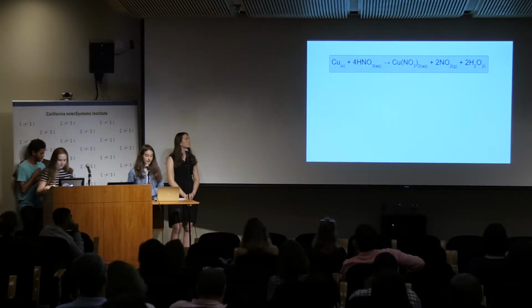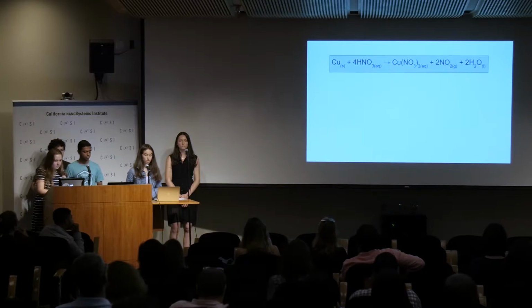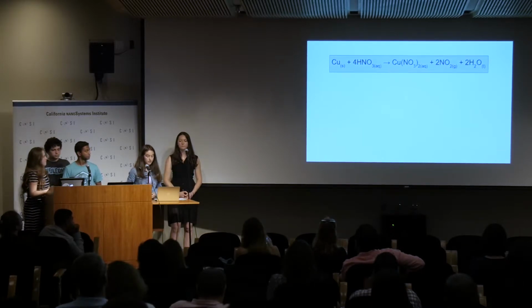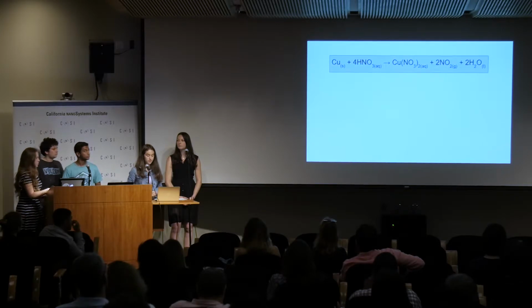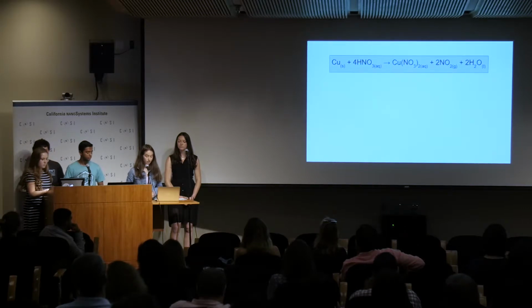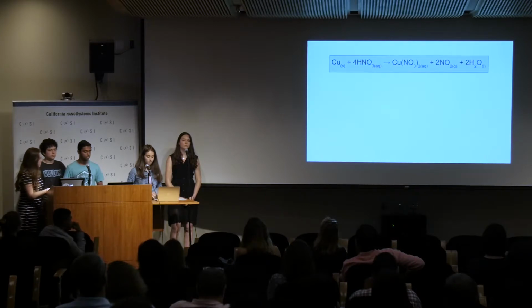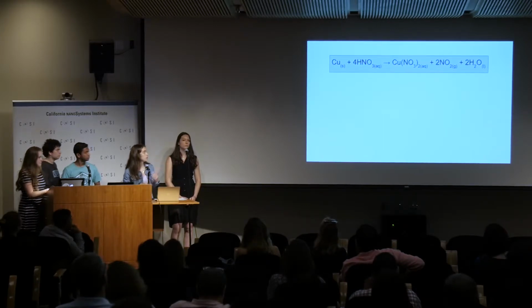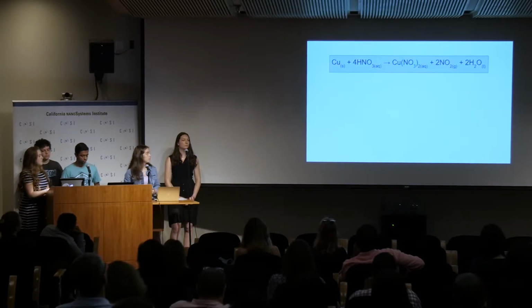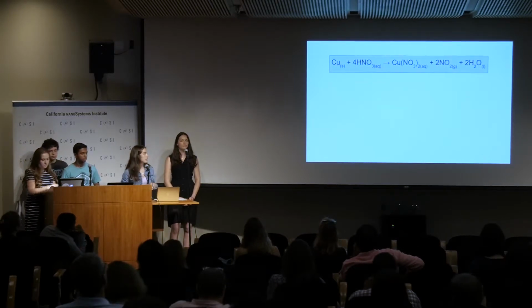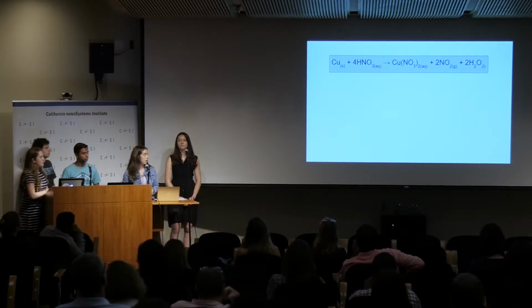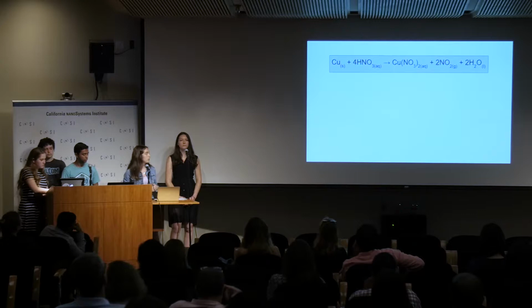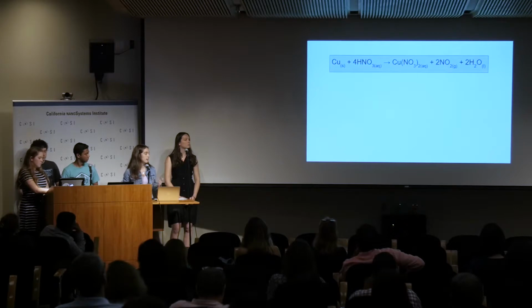We used nitric acid in our experiment to lower the pH of the water that we submerged our copper samples in, because the copper reacts with nitric acid and the nitric acid is highly corrosive to the copper. The equation above shows the oxidation reaction that takes place when copper is in the presence of nitric acid. We predict that this reaction will occur the fastest in our uncoated copper sample because that's the only sample that does not have a superhydrophobic barrier between the pH solution and the copper surface.